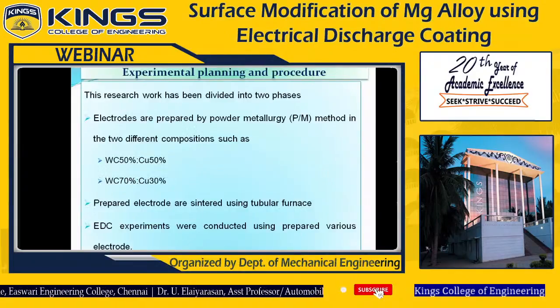Experimental planning and procedures. Before conducting the experiment, first we have to prepare the powder metallurgy electrode in different proportions. Here I have selected 2 proportions: 50-50 and 70-30. Tungsten carbide 50% and copper 50%, and the other proportion tungsten carbide 70% and copper 30%. If you take 100 grams total weight, 50 grams tungsten carbide, 50 grams copper.